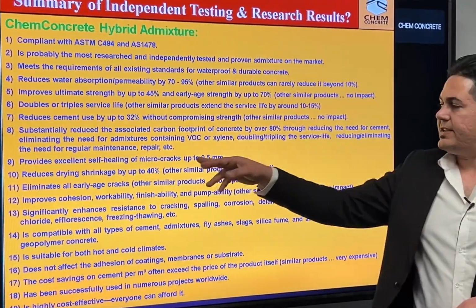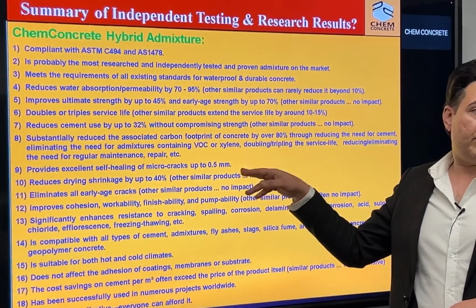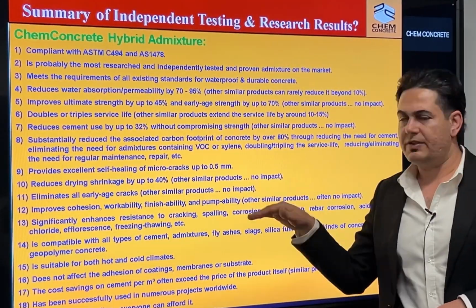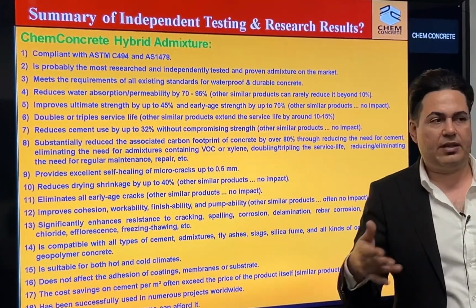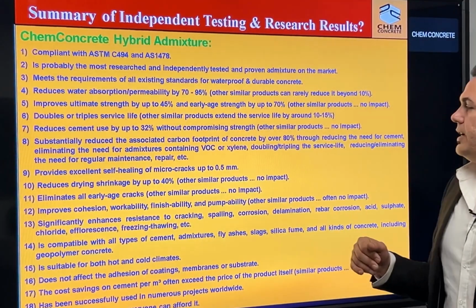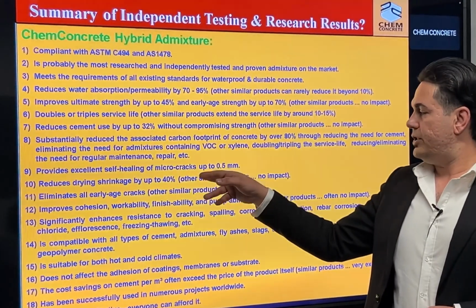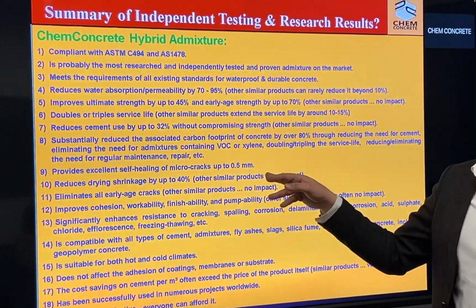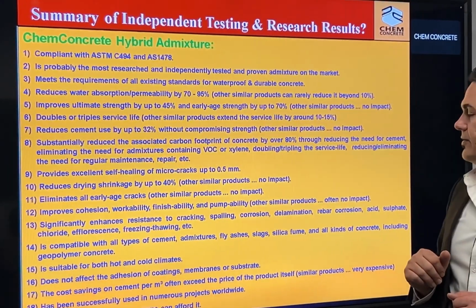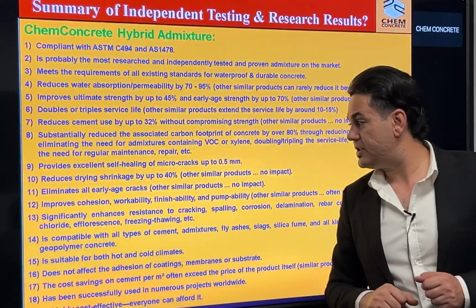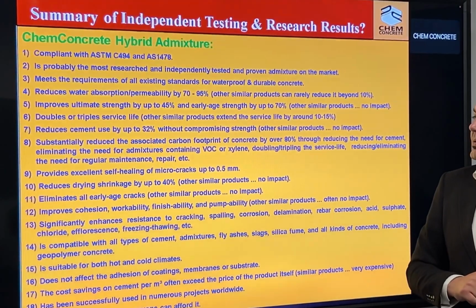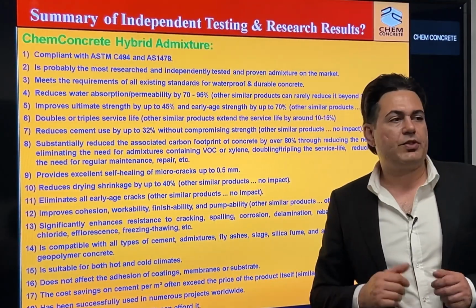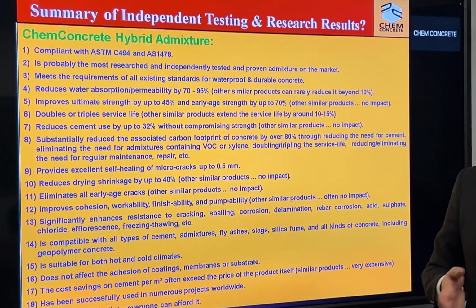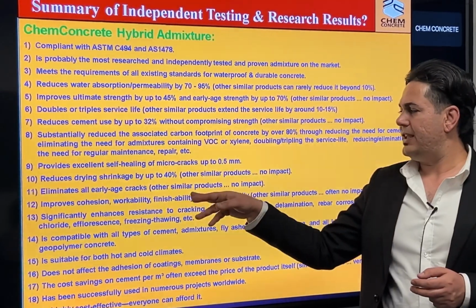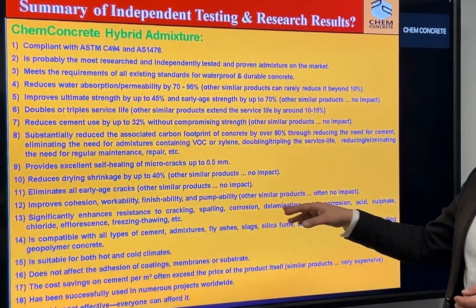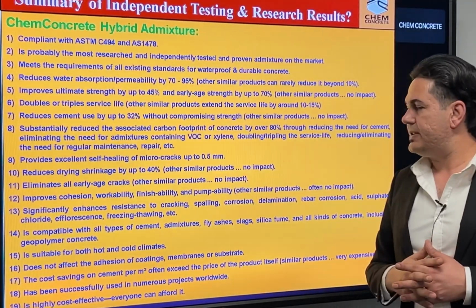So it provides excellent self-healing of microcracks up to 0.5 millimeter, which based on our experience is the highest self-healing that an admixture can provide. And then it reduces drying shrinkage by up to 40%. Other similar products typically don't have any positive impact on reducing drying shrinkage. The next one is eliminating almost all early age cracks, shrinkage, thermal cracks, and these things. Again, typically other similar products have almost no impact on these properties.